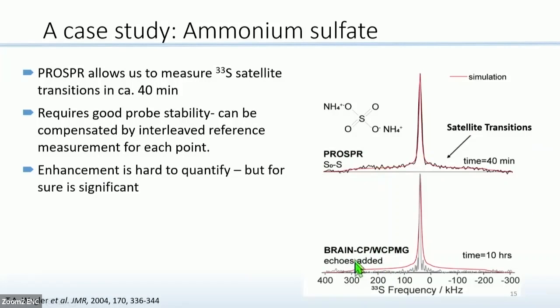The enhancement was very significant. It was even hard for us to quantify how much it is because we couldn't even observe the satellite transitions in the regular measurement. I would like to say that it does require good probe stability because of the low signal of the satellites here. So we had to acquire a reference measurement for each point here.